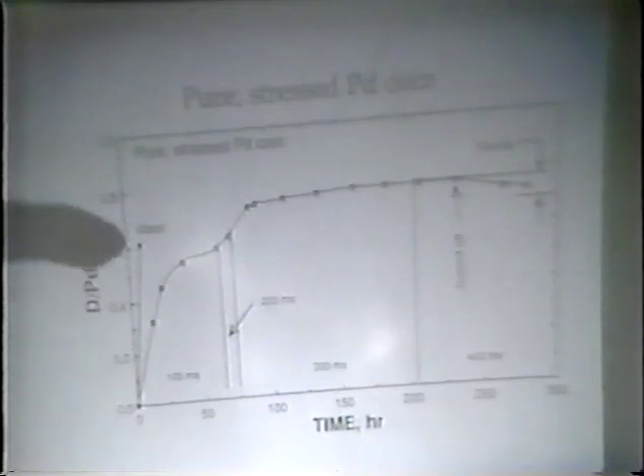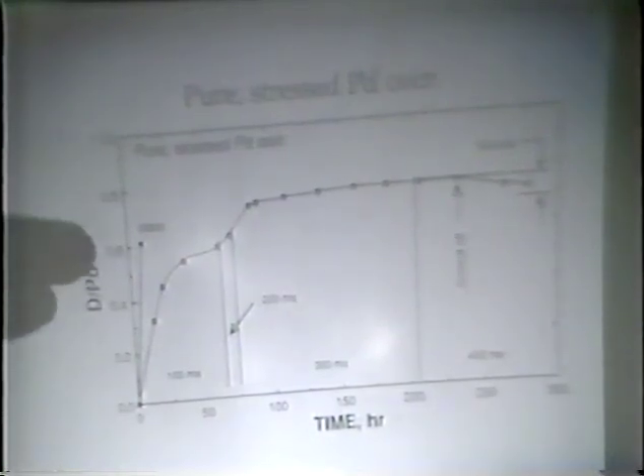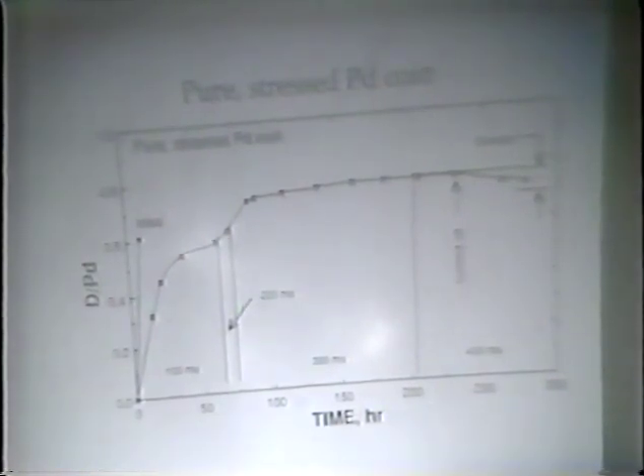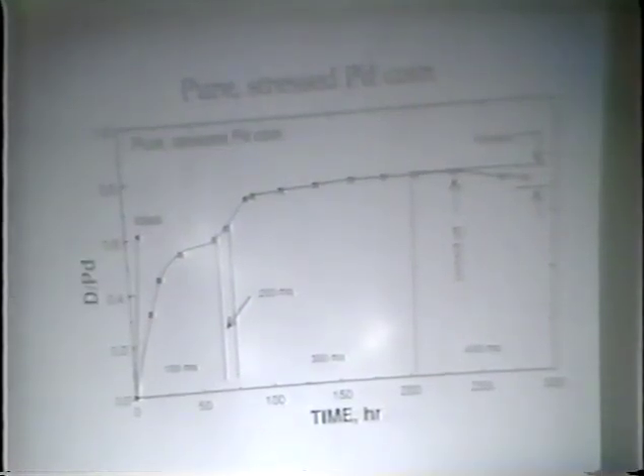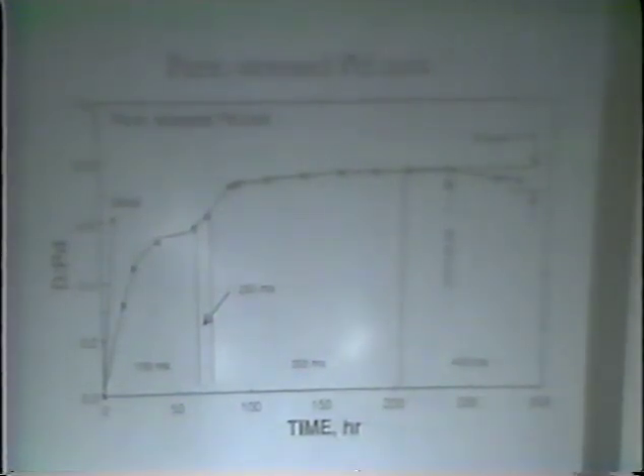The ideal line is that charging rate that you'd expect if all of the hydrogen went into the palladium that was available from the electrolytic reaction. And you see we do not put all of it in. A certain amount goes off as gas. And this leveled off at a little under 0.8, about 0.78. And nothing seemed to happen for quite some time.